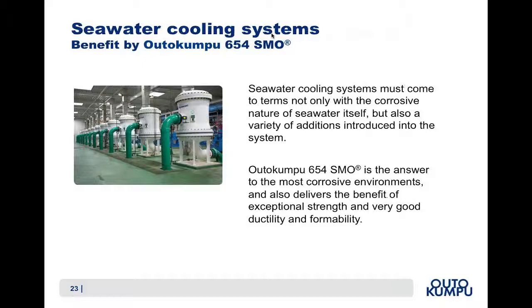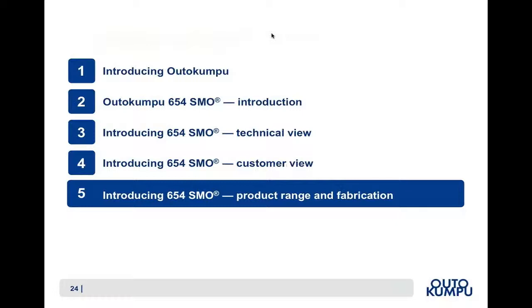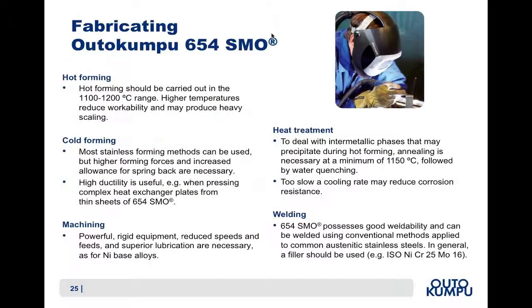Seawater cooling systems not only have to endure the corrosive nature of seawater itself, but also the variety of additions introduced into the system. And 654 SMO can often be the answer to these challenges. As with all the other grades that Outokumpu manufactures, we can also provide specific advice and technical support on fabrication with 654 SMO, from hot forming to cold forming, machining, heat treatment and welding. I won't dwell on the detail here other than to point out that there's nothing too special about welding 654 SMO, for example, and that it uses conventional methods employed with common austenitic grades.